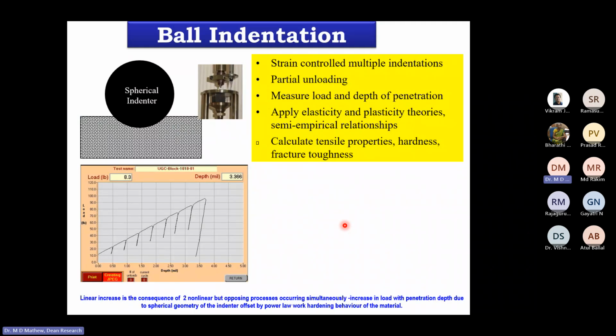So now coming to a little bit in detail about the ball indentation test. The test is basically a strain control multiple indentation. What you basically do is you have a tungsten carbide steel ball, and the ball is pushed into the material under strain control conditions. You don't push the ball in one step. You do it in multiple steps. You will initially define what is the total depth of the penetration that you want to do. That is divided into some 6 or 7 equal amounts, and then in 6 or 7 steps you are penetrating the indenter into the material, and every time you are not penetrating the material fully inside, it's only partly inside, so there's a partial unloading that happens. So it is called a strain control multiple indentation involving partial unloading.